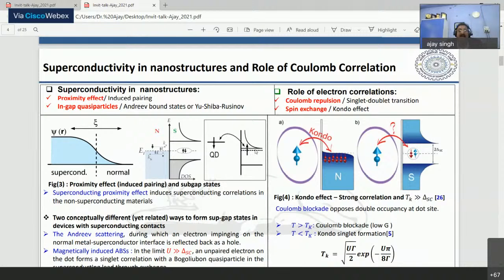So when you couple a superconductor to a quantum dot, where the dot energy level is close to the Fermi level, and the rest of the dot level energies are far away, with an energy difference larger than the superconducting order parameter, you see a very interesting effect. You see a formation of a singlet-doublet transition, which is beyond the Kondo effect. And in this regime, the two conceptually different, yet quite deeply related, subgap states and magnetically induced Andreev bound states, where U is much larger than the superconducting order parameter, can coexist.